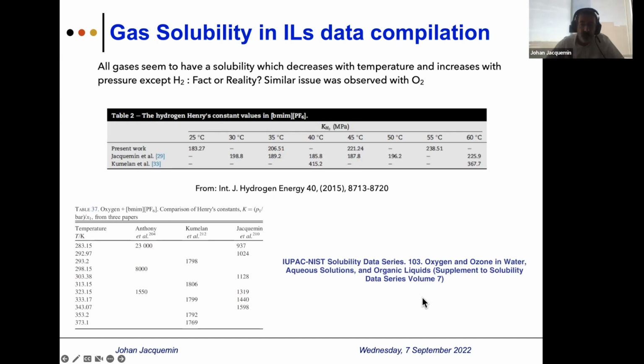data series, volume 103, because none of the data set published for ionic liquid could be really used as a recommended data. And just to give you an example, this from the SDS 103 table, and this is 3 papers, and from the Henry's Law constants, from the 3 papers at different temperatures, and all Henry's Law constants have been normally recalculated for 1 bar. And this is a group from Brennecke. This is from the group from Germany, Kumelan. And this is from my study, I would say, with Margarita Costa Gomez groups.